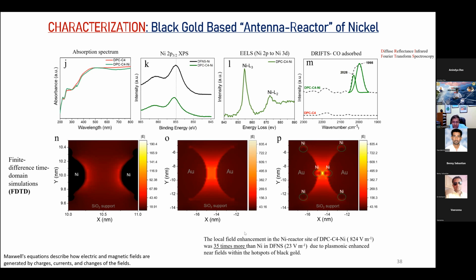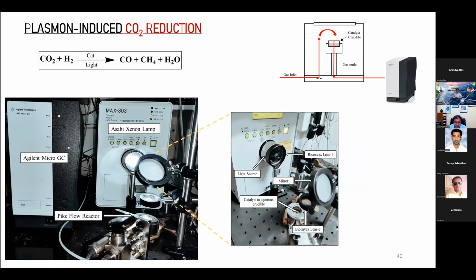In addition to these hot electrons and thermal energy, you also have a polarizing electric field produced during the surface plasmon resonance, and between the gaps of these particles we call them electrical hotspots. If your reactants are in these hotspots, they get polarized. CO2 will bend, the bond length will change, and that activates the CO2, lowering the activation energy barrier so you may do the reaction at lower temperature simply using the hot electrons. So several things happen positively when I use the concept of surface plasmon resonance. This is how we do catalysis.